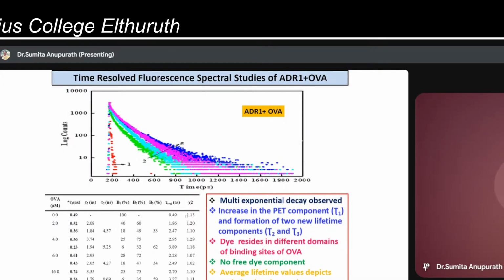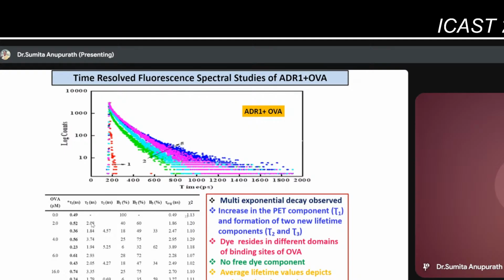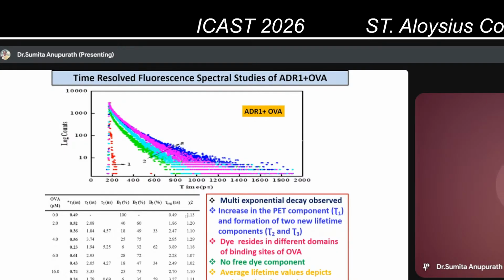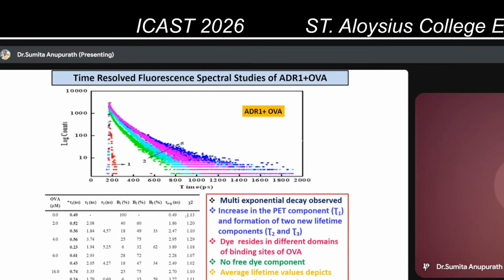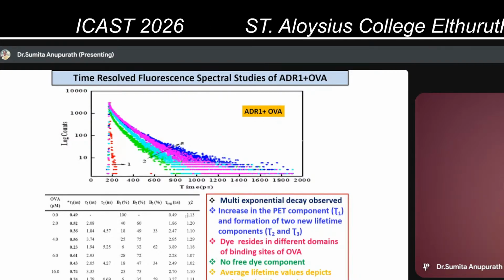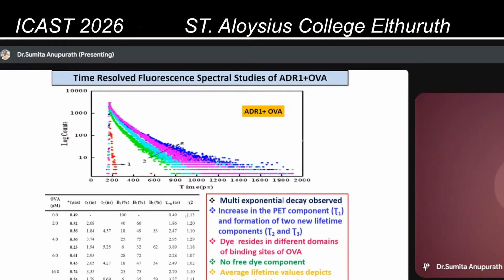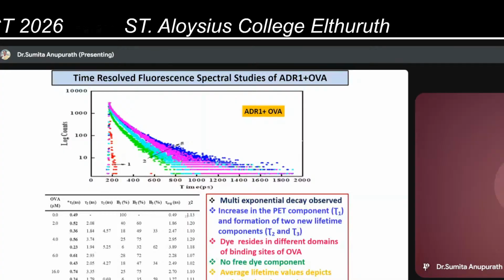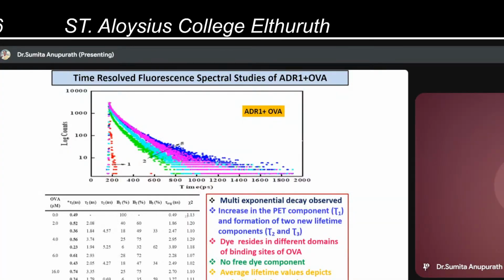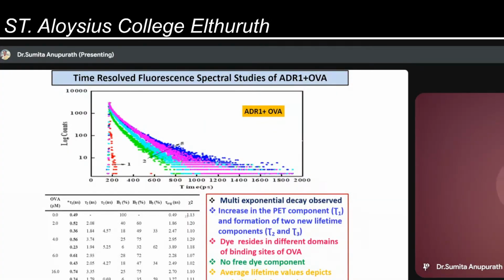And apart from that, the data also revealed that two new lifetime components were formed, tau2 and tau3, which is again due to the formation of different microenvironments. And those microenvironments were formed because the dye resides in different domains of the ovalbumin. One interesting factor which was found is that there was no free dye component present. That is, the dye was completely trapped in ovalbumin.